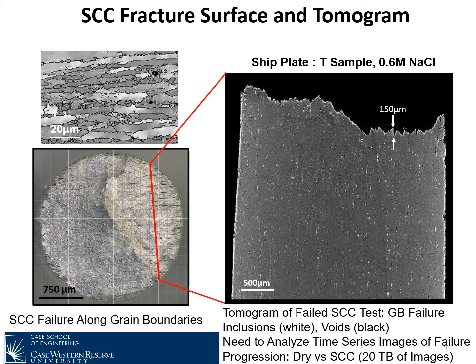This is a relatively low resolution scan here, but you can see there are a lot of white dots, which are inclusions in the material that are elongated along the rolling direction. There's also voids that are black that are hard to see at this magnification. So what we need to do next is to analyze the time series of images that were obtained in those tension tests, because there we'll be able to see the failure progression on a dry situation, which is, if you will, the best the material is going to behave, and then under this stress corrosion cracking condition. So these will be 3D volumetric images and about 20 terabytes in character.